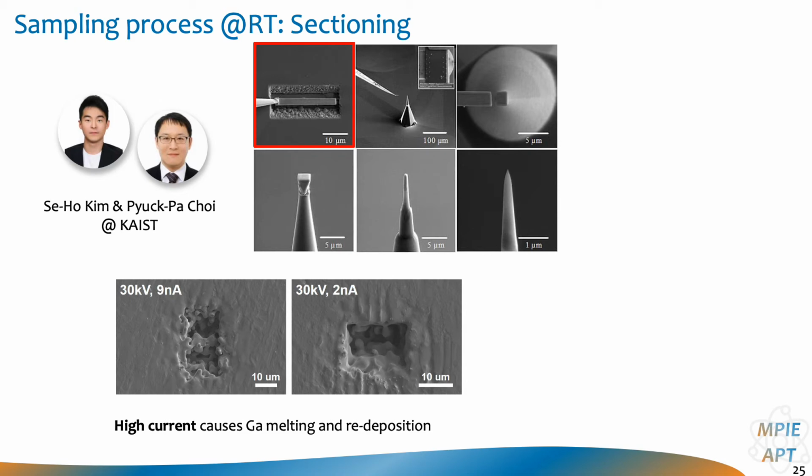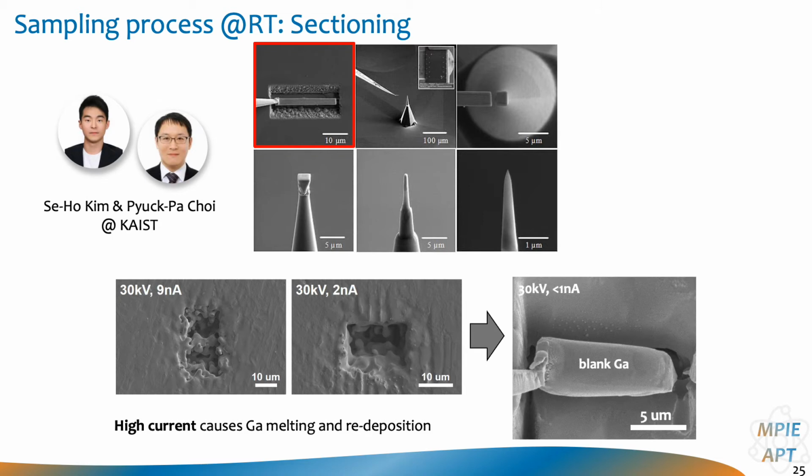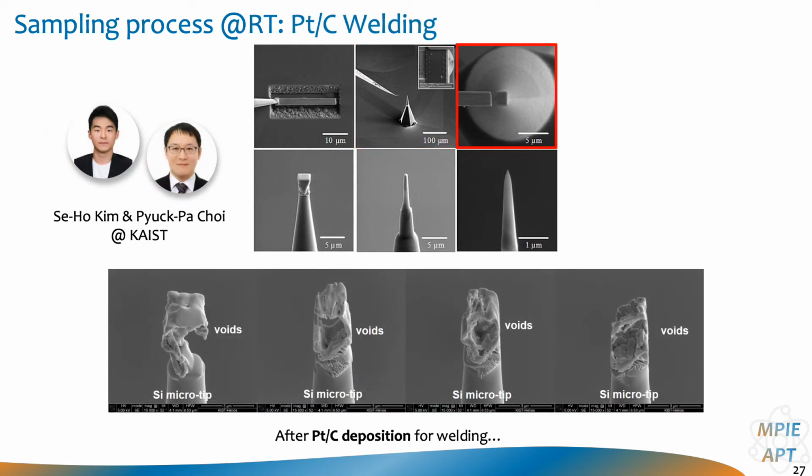The thing is, the gallium melts at very low temperature, as I've said, so when you want to try and do the typical lift-out protocol, it becomes really quite tricky. It melts during the FIB-ing itself with gallium. And even when you manage to do it, it's difficult to turn this into a needle afterwards. It creates voids and typical melted structures, so using this as an approach seemed to be a bit difficult, let's put it this way.